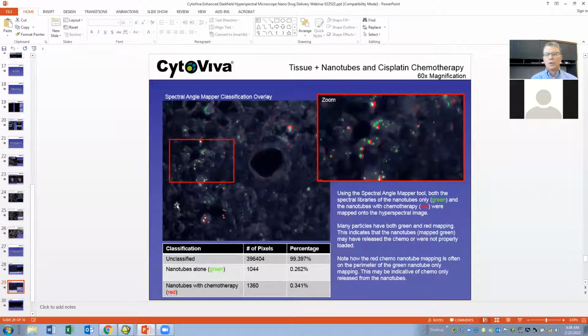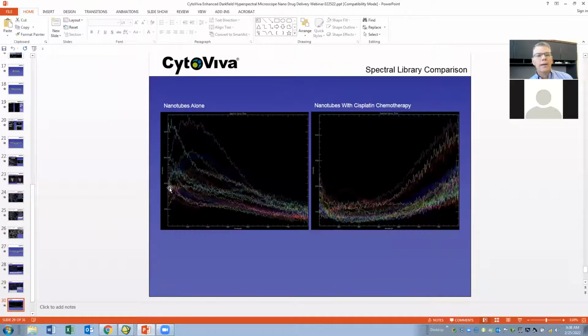And here we're doing mapping of two things. We're doing mapping in the red of the nanotube chemotherapy, and then nanotubes alone are in green. So what we see is that in the red, we see lots of release of the pharmaceutical active ingredient, and in green, we're looking at the nanotubes alone to demonstrate that. Here is the spectrum of the nanotubes alone. Here's the spectrum of the nanotubes with the cisplatin chemotherapy, to demonstrate that the functional groups added to these really change their optical spectrum.